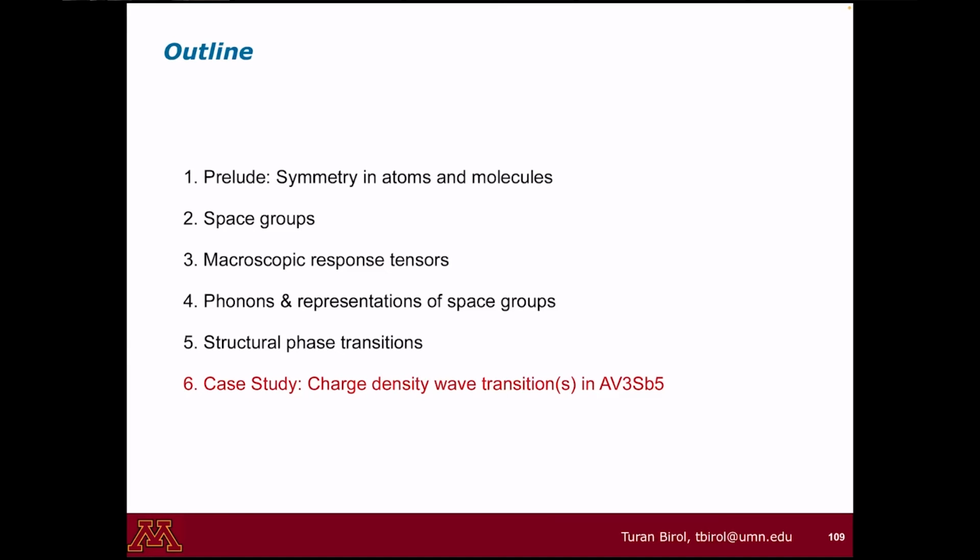So if you were a spectroscopist and you were talking about a transition, for example, the order parameter of that transition always becomes A1g or gamma 1 plus, the so-called trivial representation, below the transition. And again, Raman people really like this. This is how they understand the degrees of atomic displacements and so on. But when we are writing the free energy expansion and so on, we need a starting point and we need to keep that starting point consistent. So we always use the representations of the high symmetry space group, the high temperature, reference space group. Does that answer your question?